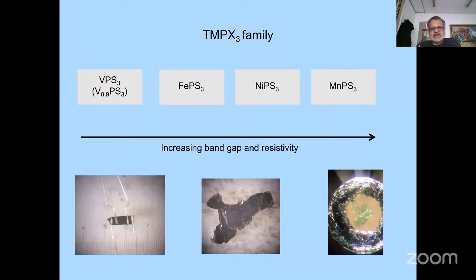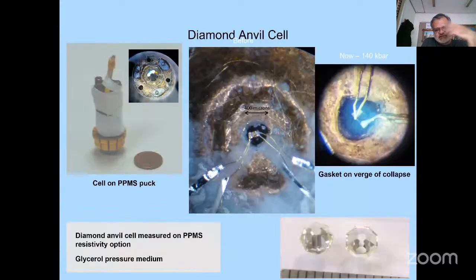This is the chemical formula of the materials that we are discussing, and you will notice that within this family, there are 2D antiferromagnets which are hexagonal and honeycomb in structure, and they're layered materials which can be peeled, all of them. But as you go from iron to nickel to manganese, we find that the band gap increases as it goes up, and you can see it, even the color can tell you that. But this turned out to be very interesting, and just for the experimentalists, this is how we do our experiments for these materials.